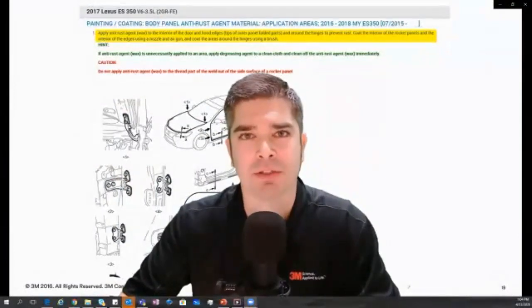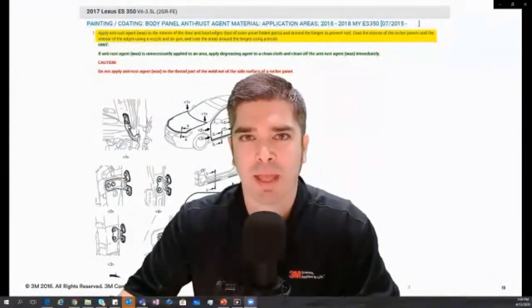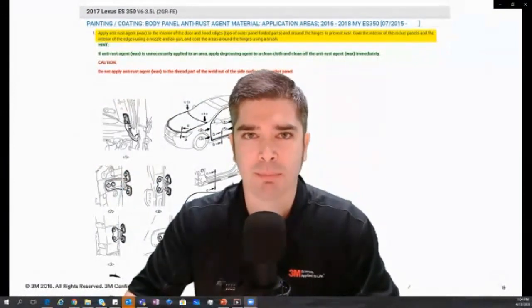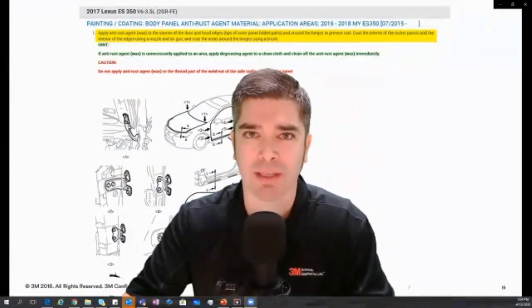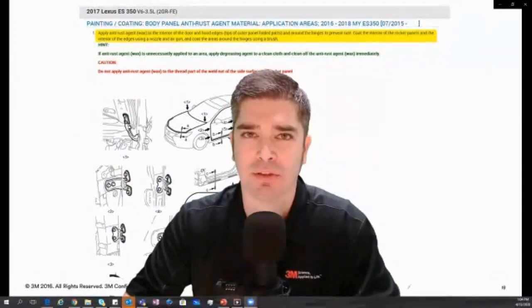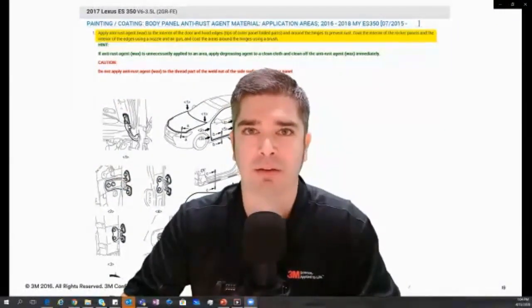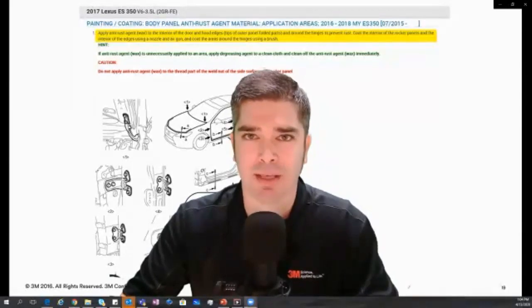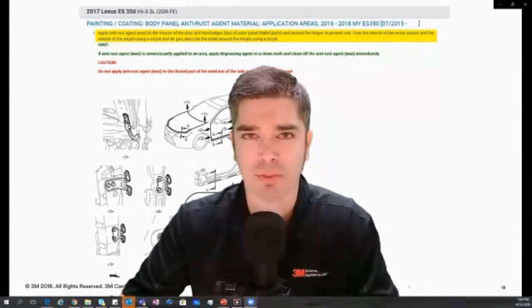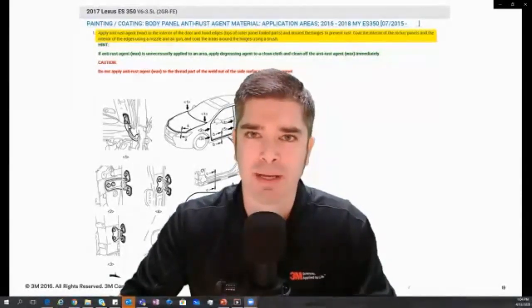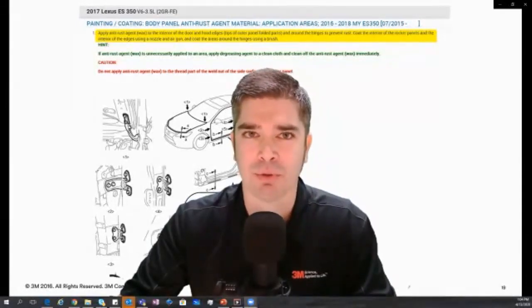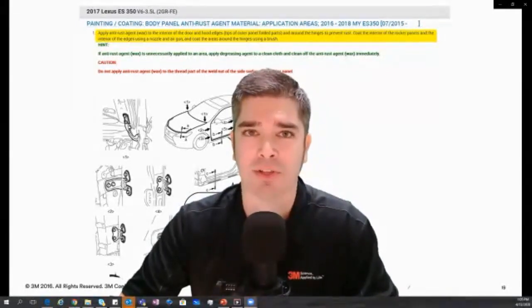Right. So those are some great points. And like Sean mentioned in that video, having these coatings in there, potentially pooling up and blocking some of these flanges that need to have cavity wax wick into these locations because of the use of a primer, might still leave bare metal in there. So it's important, again, to think about the best application in blind areas. If you think of a quarter panel, say the backside of a taillight pocket, those things are pretty easily accessible in most cases, to get in there and clean them up and properly prepare them and then apply top coatings or paint material on top of those.